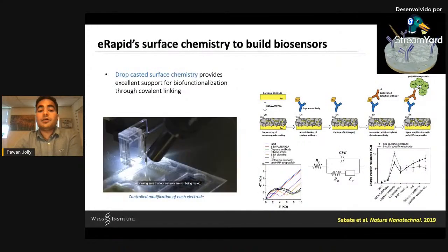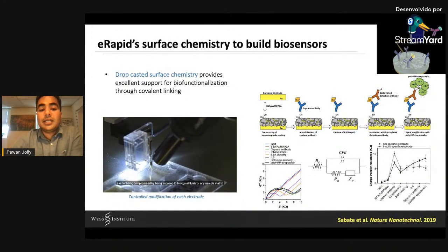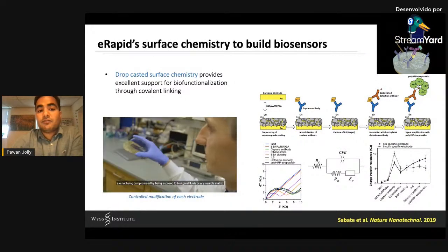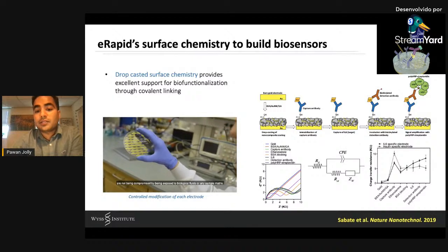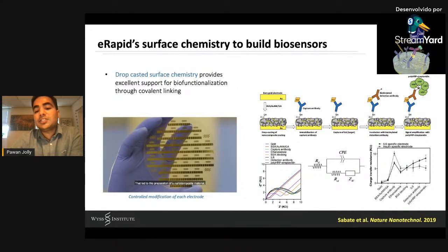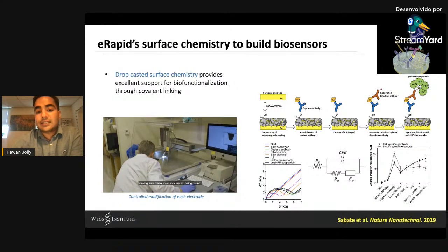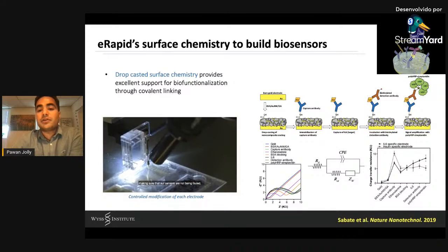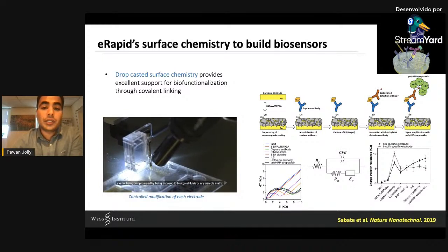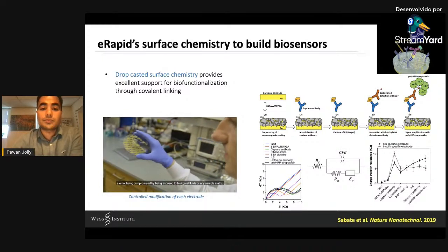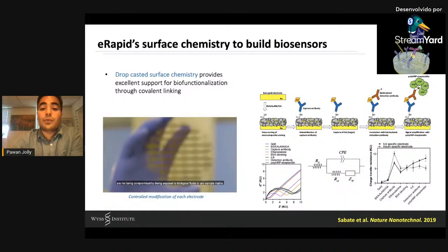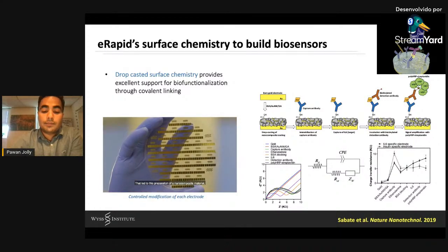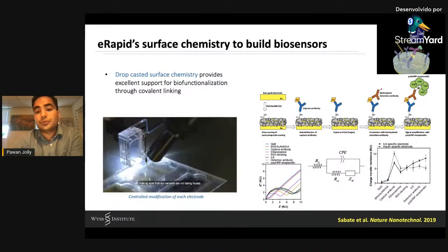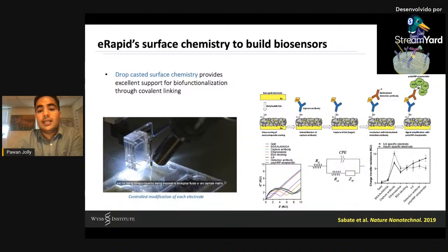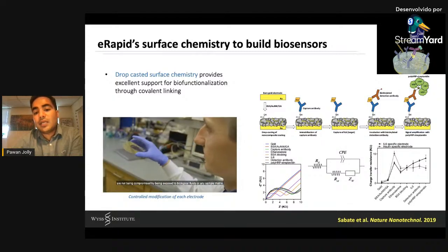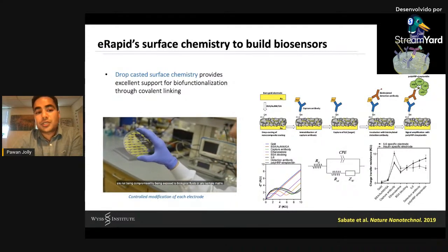So taking a step further, we wanted to characterize each layer-by-layer modification. And for that, we use electrochemical impedance spectroscopy, which is essentially looking into the charge transfer resistance. So basically we have a redox probe in the solution and we are looking into the resistance that the redox probe experiences while diffusing from the solution to the electrode surface. So essentially when you coat any metal, you should see an increase in the charge transfer.